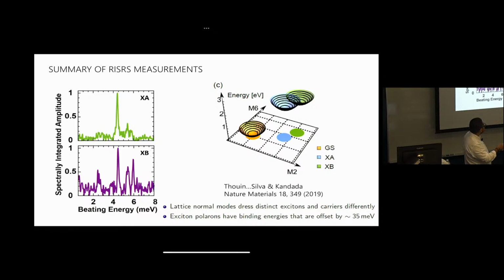This is the energy of the excitons with respect to the ground state, and the displacement tells us we've excited to these exciton states, and there's a local lattice deformation. That's what that represents. There's a local lattice deformation that is different for exciton A and exciton B. So exciton A and exciton B are dressed by phonons in a very distinct way. They're not the same species. They're not the same optical transition.